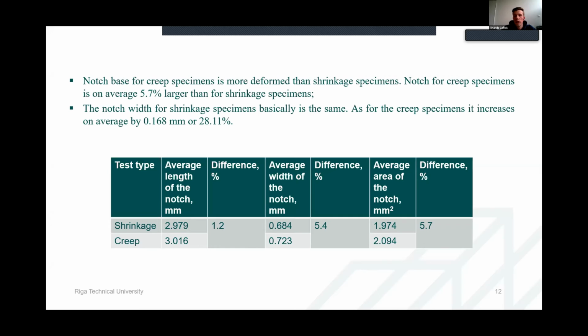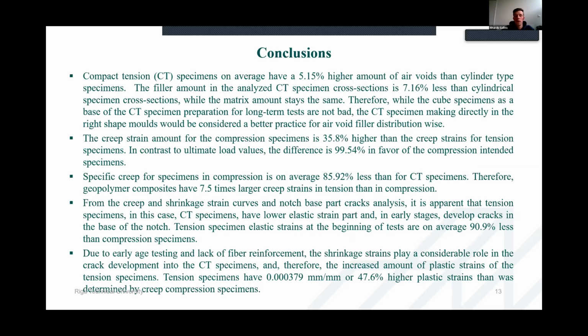So further analyzing the notch area, we can determine that for the creep specimens, there is a significantly larger area of the notch. It's 5.7%, but even more if we measure the opening of the notch at the beginning of the polished section. We can see that the notch opening there is 28.11% larger than in the shrinkage specimens. So we're thinking that after the creep test, there is a significant amount of deformation that has happened that is not elastic.